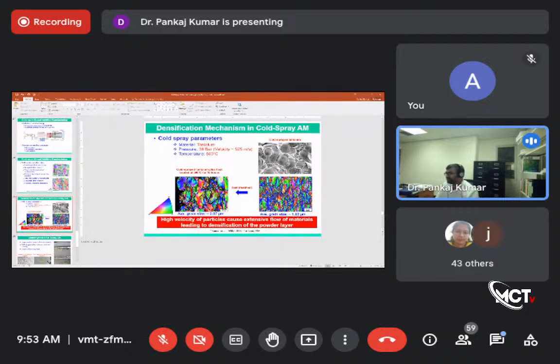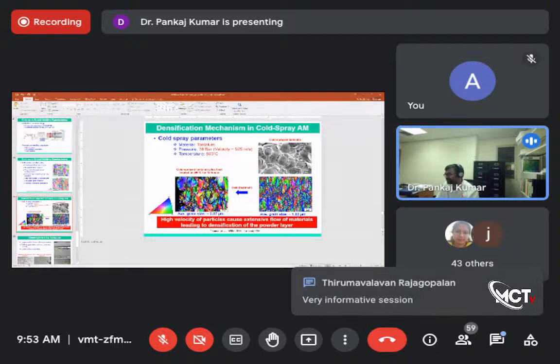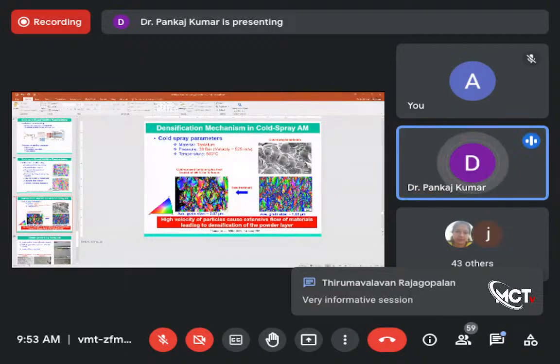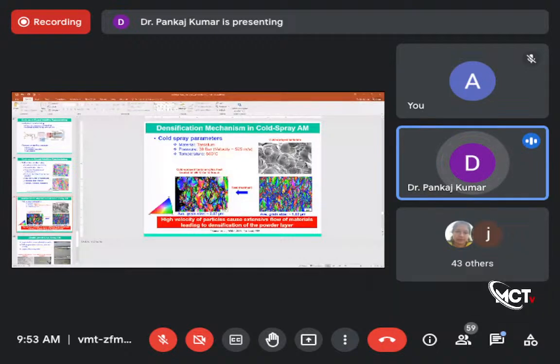Excuse me. So these are the tantalum particles, and you see the interface, right? So tantalum particles, depending on what the particle size is, you have the surface roughness. Okay, so you have the surface roughness. So you can control the surface roughness. That is a challenge, and you don't want to use the rough component in your applications, right? You always want to have a very finished, very fine surface. So this is the challenge that we really need to worry about, right?